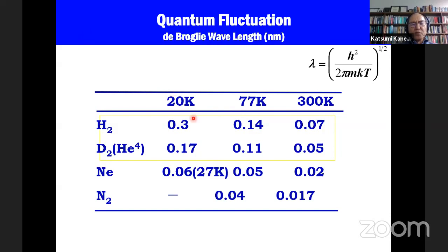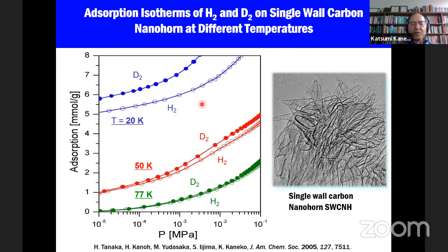Very qualitatively, for example, I show some extent of quantum fluctuation. This is evaluated by de Broglie wavelengths. For example, at 20 Kelvin, the boiling temperature of H2, the de Broglie wavelength is 0.3 nanometer, and for deuterium D2, 0.17 nanometers, very different. If the adsorption is in 0.5 or 0.7 nanometer pores, this difference cannot be neglected.